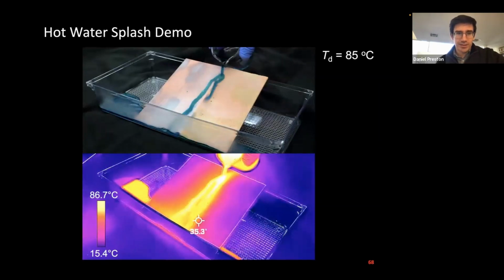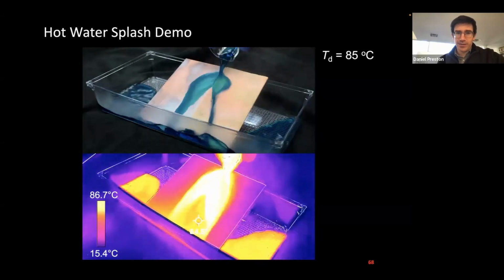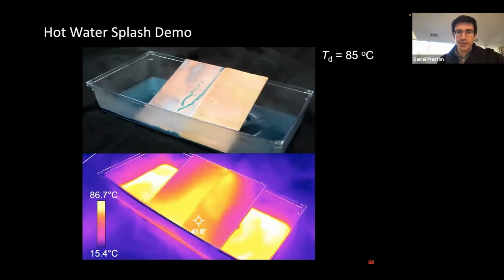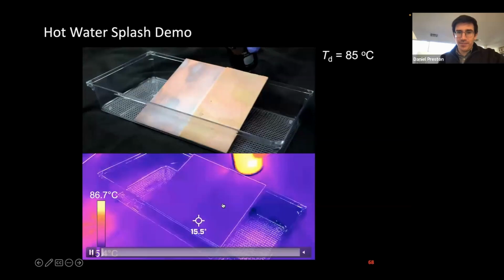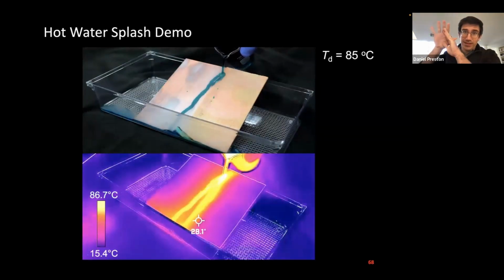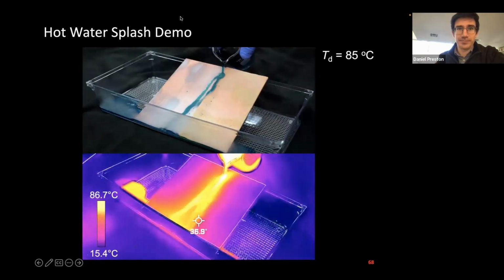These should be synced up to each other. Quite hot water is poured on the surface. Both sides of the surface do get hot, but on the right-hand side, the top layer of the surface gets hot, but it stays hot and does not penetrate through to the bottom.